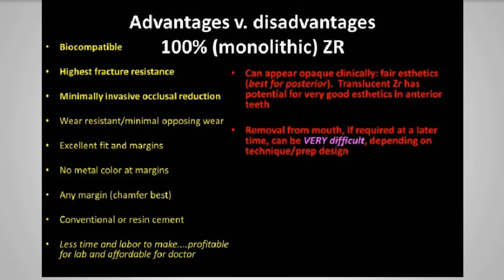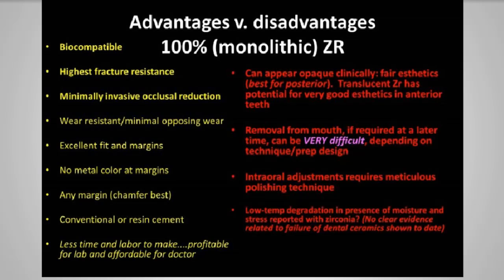Removal from the mouth, note this in the light purple, is very difficult, depending on the technique and prep design. We'll talk more about that. Intraoral adjustments require meticulous polishing technique. Low-temp degradation in the presence of moisture and stress has been reported with zirconia on the medical side of the house, but no clear evidence yet related to failure of dental ceramics has been shown. But we'll see with time. More long-term in vivo research is needed with zirconia in general. But we're getting there. We're starting to understand this material more and more as we go.